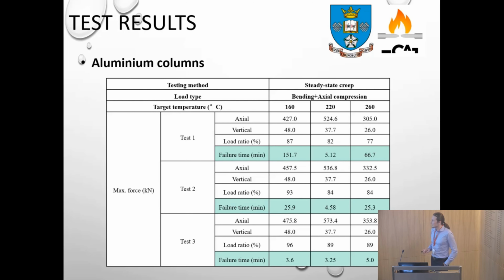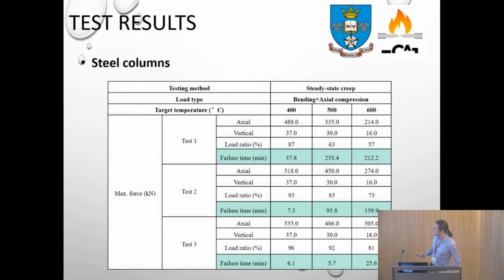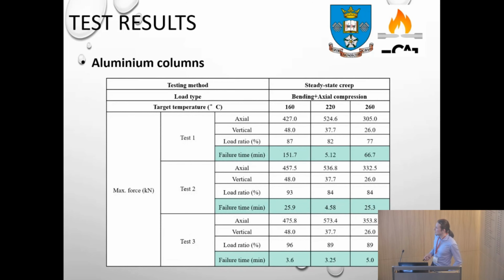The aluminium columns had a behavior with respect to creep much worse than steel. For example, the temperatures that we tested were between 160 and 260 degrees. The load ratios were also high, but the overall conclusion is that the columns suffered very quick failure time if the load ratio was 90% or above. And in comparison to steel, the aluminium columns had a very low failure time. So the steel columns could exist much higher failure time in comparison to aluminium columns.